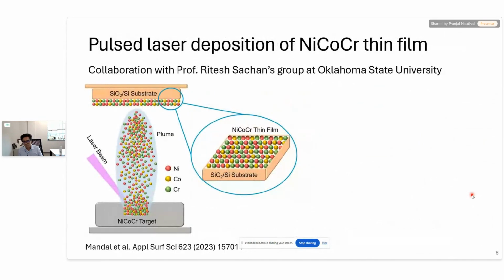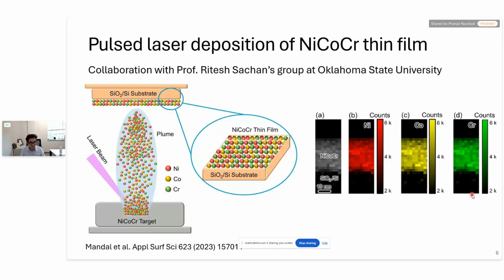So we developed nickel, cobalt, chrome alloys. So we started with a medium entropy system. This work was done in collaboration with my colleague, Professor Ritesh Sachan's group at Oklahoma State. Their group specializes in pulse laser deposition of high entropy materials. So they deposited nickel, cobalt, chrome thin films with a thickness of about 100 nanometers for our tribology studies. And then they confirmed the structure of these films. And as we can see here, there is an equal uniform distribution of nickel, cobalt, and chromium throughout the film. Okay, so that's the sample we used for this study.